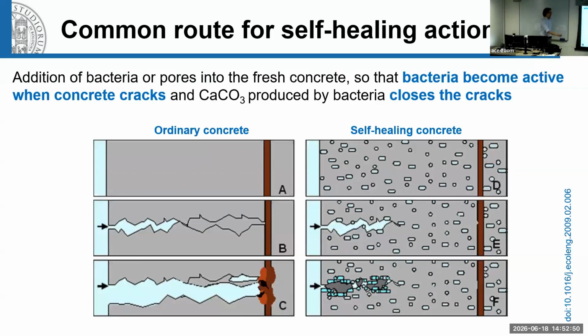This has been exploited because when you have ordinary concrete with no self-healing action, nothing strange, you have the concrete, you have the steel bar, you have problems when the concrete cracks, so that water, oxygen, and so on can reach the reinforcement bar, and so you have a corrosion starting. The idea of this self-healing concrete is to include in the concrete capsules containing the bacteria or spores of the bacteria. So when the concrete starts to crack, the capsules containing the bacteria are cracked open, they release the bacteria. The bacteria form calcium carbonate and are able to close the crack before it reaches the bar. And so you are able to prevent or at least delay the corrosion of the steel bar.